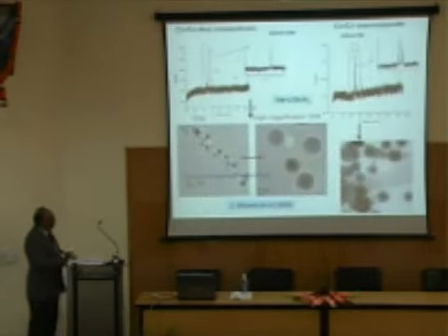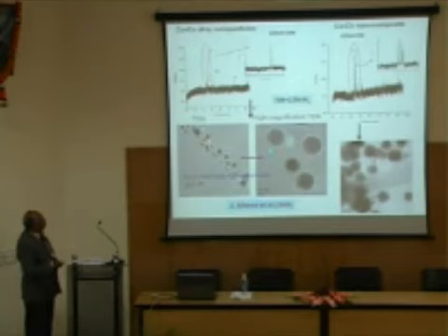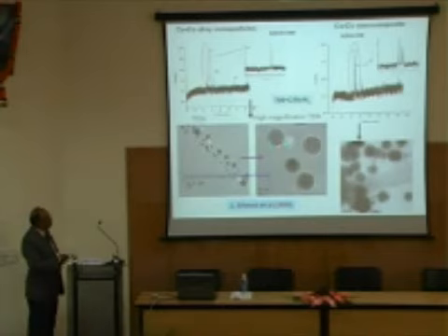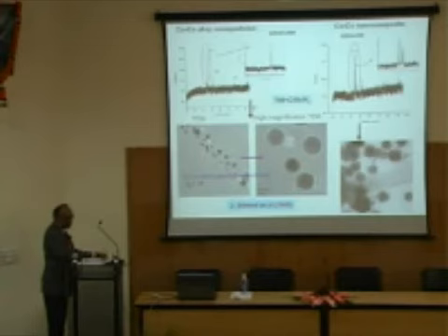Then you can also make copper cobalt, one over the other. This is what we call a core shell structure. You have a core of one metal, on top you have another metal, and this is of the order of maybe 80, 90 nanometers, this is large. However, if you change the procedure, you will get copper and cobalt as separate particles growing on each other. Here it is one particle growing on top of another, but here you have like a composite, both particles growing together.